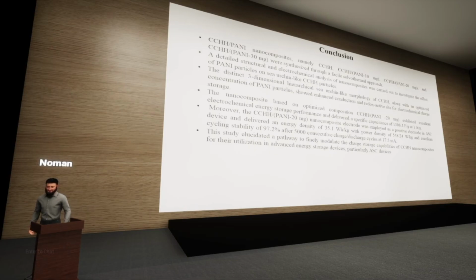Moreover, the energy density of 35.1 watt-hour per kg with power density of 548.21 watt per kg was shown, with cyclic stability of 97.3% after 5,000 GCD cycles. And this study shows how the cobalt carbonate hydroxide hydrate nanocomposites can be used for energy storage device applications.